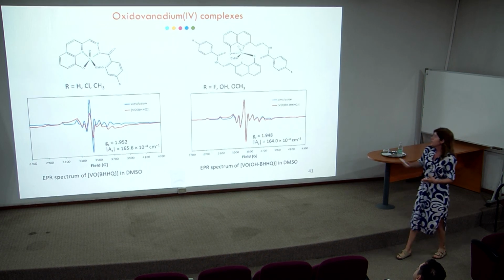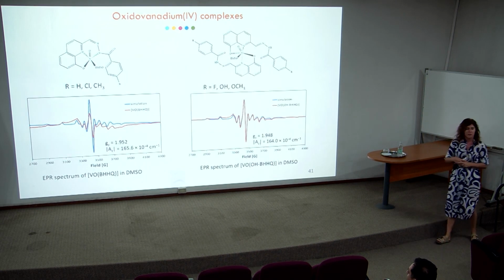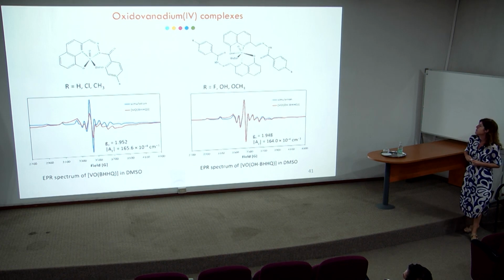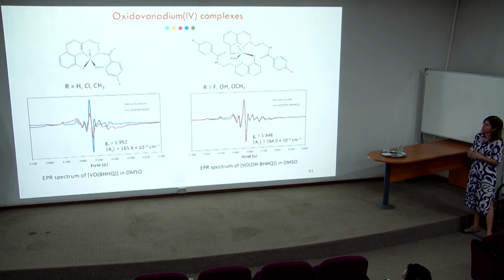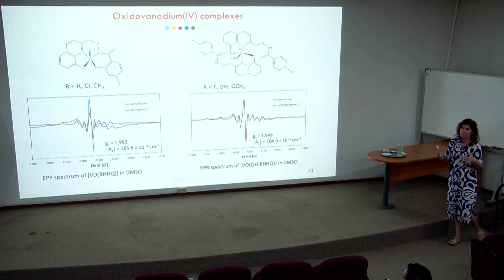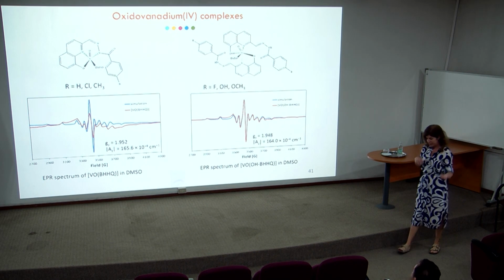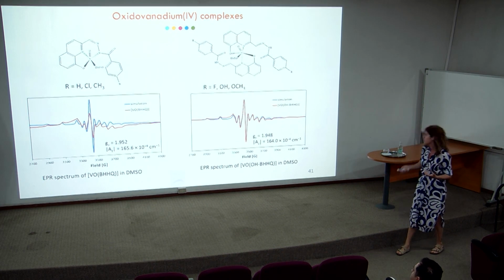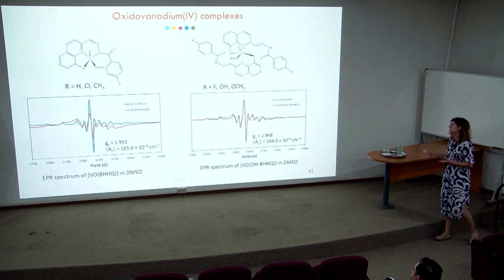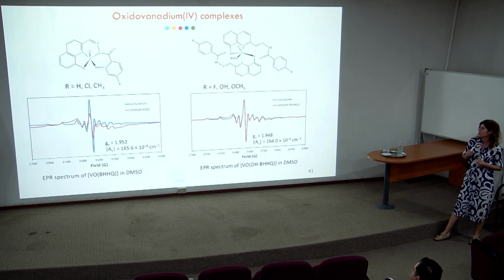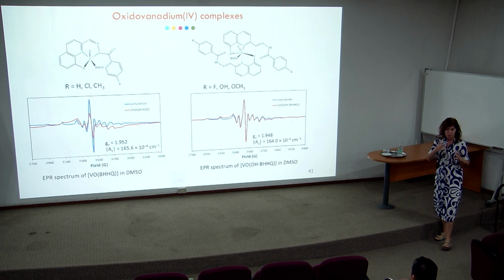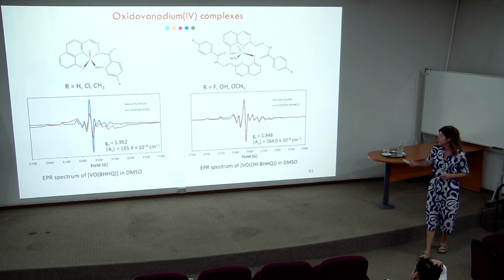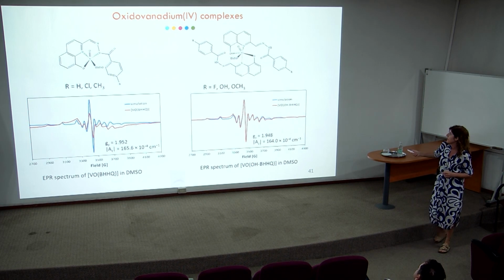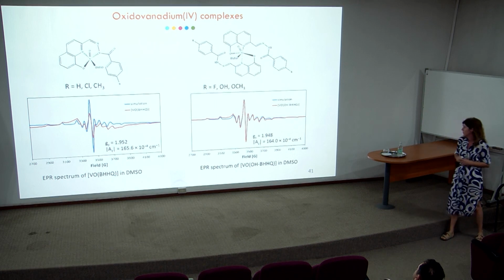We also prepared the oxidovanadium-4 complexes, characterized them by EPR. In the case of copper, in all the syntheses, we obtained 1-to-1 ligand-to-metal complexes. In the case of vanadium, some systems we obtained 1-to-2. And for vanadium, there is a preference for coordination through the 8-hydroxyquinoline chelate and not through these side groups.